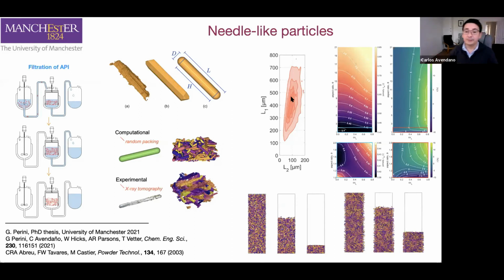But again, depending on the temperature at which you run the experiment, you could have different sort of distributions. But we decided to use Monte Carlo simulations to analyze the packing of different distributions, and we came up then with these results, where we can observe that to maximize the porosity of the systems, we have to increase the average aspect ratio of the system. So as soon as we move up here, we can see that the maximum porosity is reached around here.